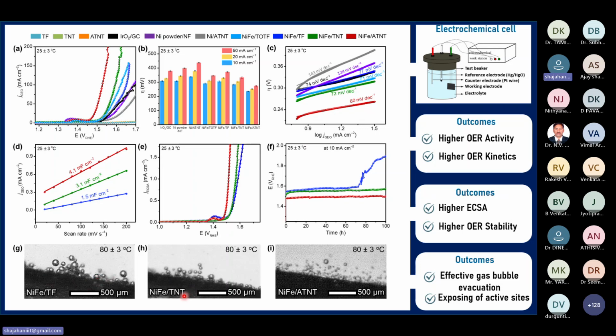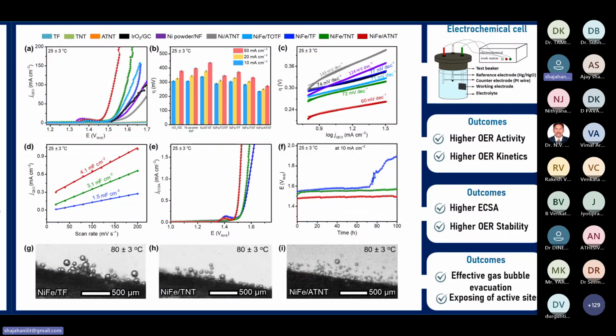In the case of TNT, this region is smaller, but we can still see some dead zones. In the case of NiFe/ATNT, almost no dead zone was observed. That means it effectively removes the gases from the electrode surface and improves the lifetime of the catalyst.